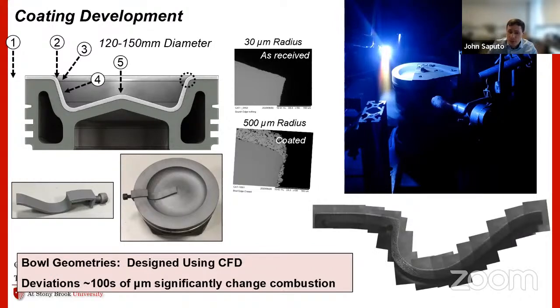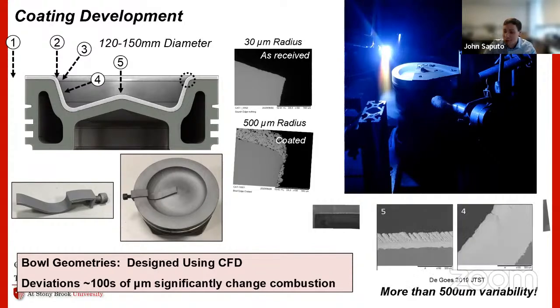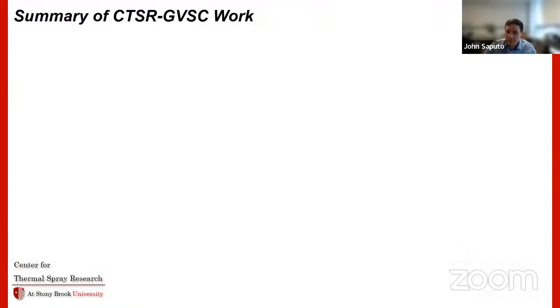So that's really important to do because the bowl geometries in these high performance diesel engines are often designed using computational fluid dynamics. And people often predict that deviations on the order of hundreds of microns in these systems can cause a larger change to the combustion process than the presence of the coating, which is kind of interesting. If you go back and look at the literature, you'll see a lot of examples of coating variabilities across the piston profile that vary by as much as 0.5 millimeter, which would make decoupling the effects of the change in bowl geometry versus the coating materials in these systems basically infeasible.